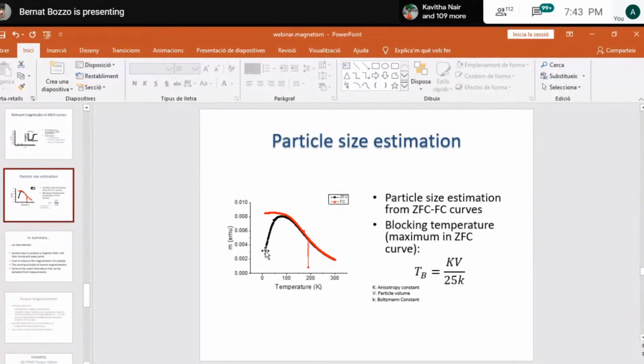At low temperature, as you heat up, your particles start to show no magnetization. You have to remember that this is a small power field, and the low temperature is not enough for fully magnetizing your particles. You will have the appearance of some ferromagnetic domains inside it. As you increase the temperature, the effect of temperature will start to promote one domain with respect to the others. This will cause an increase of magnetization.